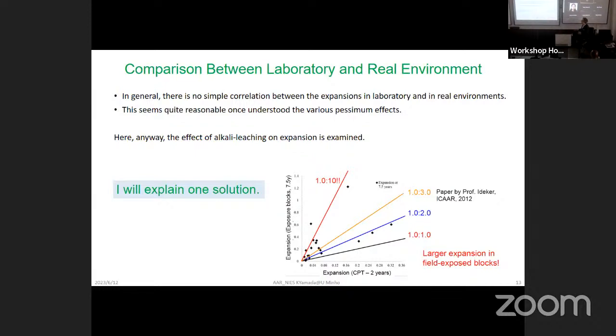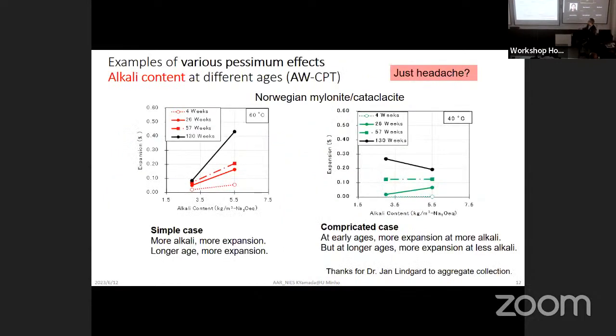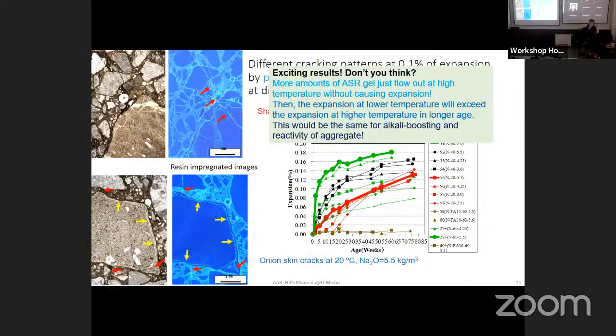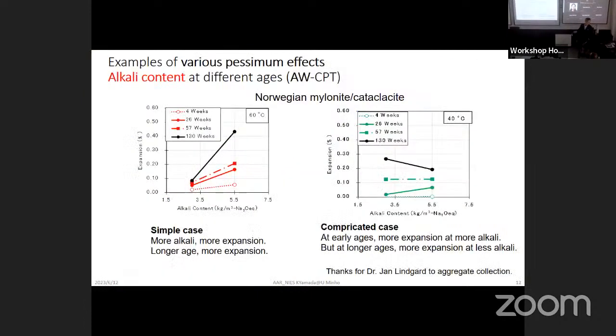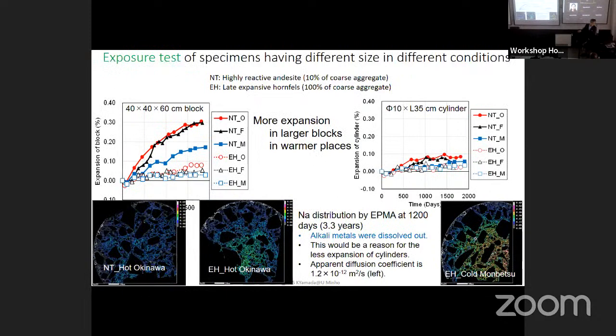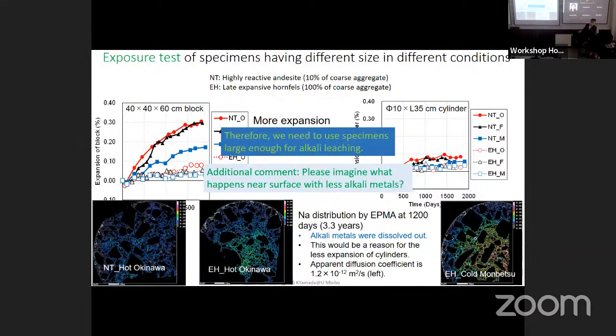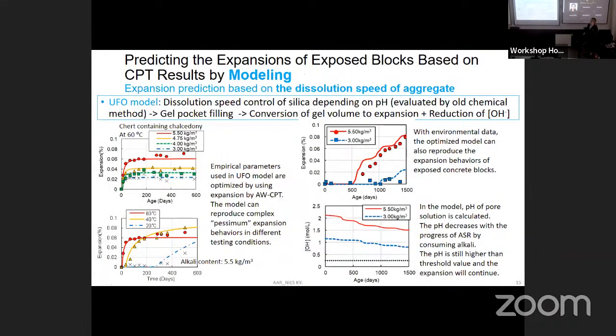Concrete prism test for 2 years. During 2 years, from concrete prism without wrapping, a significant amount of alkali was lost. They estimated, but reality is a bit different, as explained like this. Mild acceleration results in more expansion in the end. So then we need some model.